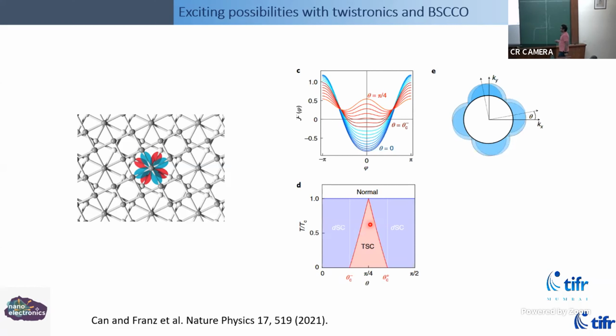Now, what they said is that if there is another process, which is co-tunneling of Cooper pairs, you can get what is called a topological superconductivity. This is all theoretical prediction. Tunneling of Cooper pairs gives rise to a topological superconductor at the interface. It will be time reversal symmetry broken, and it will last all the way up to 70 Kelvin, or up to the Tc of the system. But you have to twist the layers of the two superconductors close to the 45-degree angle.